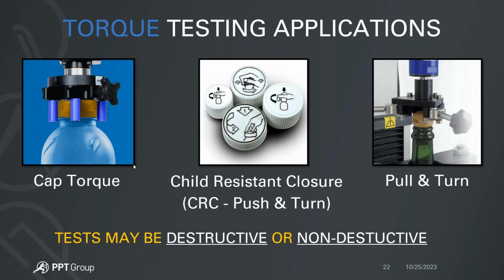If those numbers are inconsistent, another thing you can do is simulate what that capper is doing by applying actual application torque to your containers using a tester and then running release torque values to see if you see the type of results that you expected just in the beginning, right? So if those numbers are off, then you can confidently say the capper is not doing its job or it's applying uneven torque to your samples. So it's time to revisit and see how that process can be corrected.